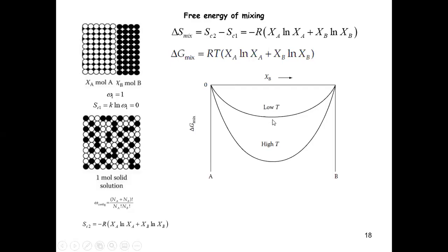The role of temperature is the following. If you have high temperature, you enhance the role of entropy. If you have low temperature, it's fine, you still want these two states to have a negative free energy. But when T goes to 0, you see that the entropy of mixing won't play any role here. So now the question for you is: for a given temperature that is greater than 0, based on our analysis, which state is more thermodynamically favored, or more stable at a finite temperature, the mixing state or the demixing state? Mixing state.